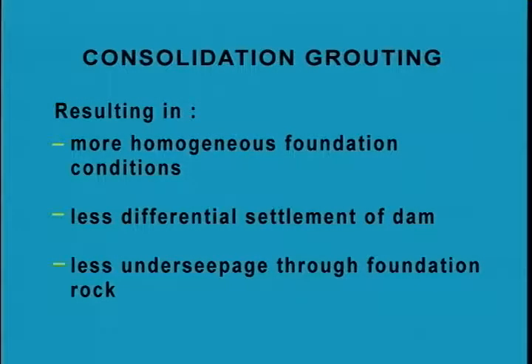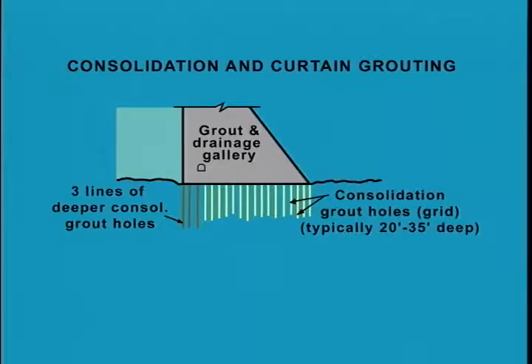By filling the more open fractures and joints completely or almost completely and thinner fractures partially, grouting homogenizes the foundation rock, leading to less settlement of the dam and less under-seepage. Consolidation grouting is required for almost every concrete arch dam, for most concrete gravity dams, and for some embankment dams depending on dam height, foundation type, and the philosophy of the designer. On several recent projects I have recommended increasing the depth of consolidation holes by up to 50% for the two or three lines upstream of the future deep grout curtain.